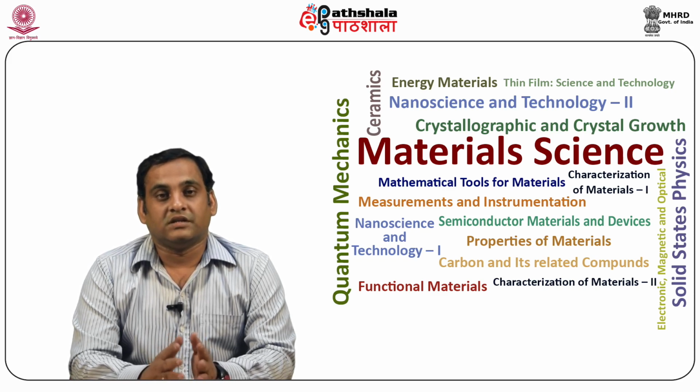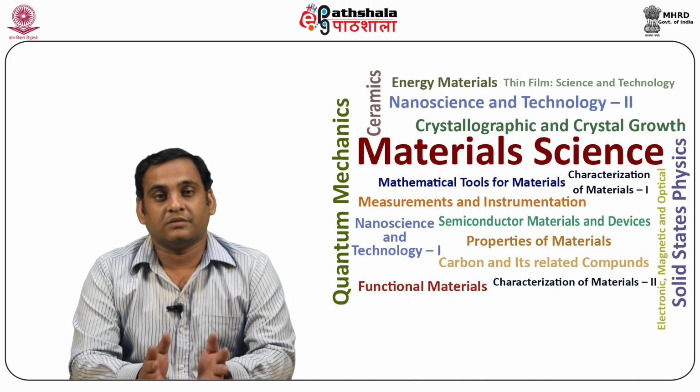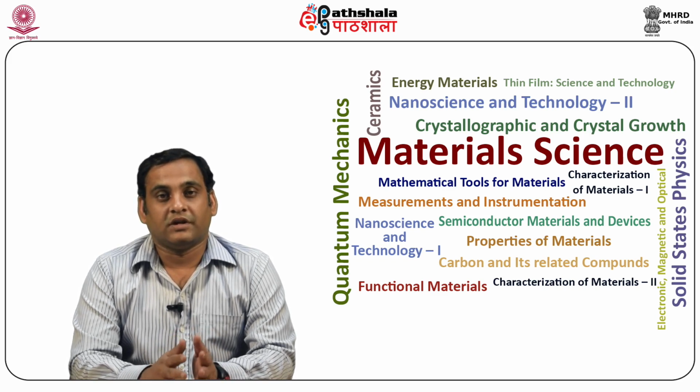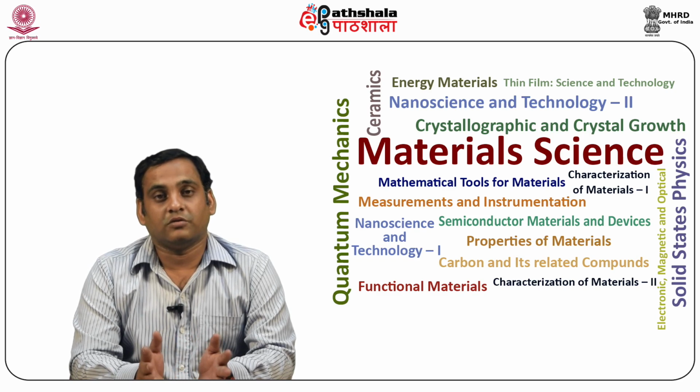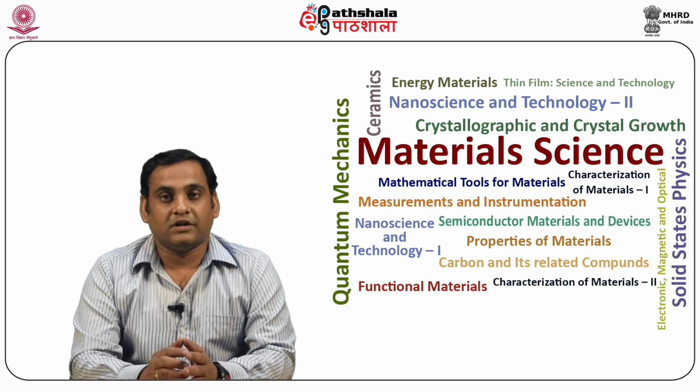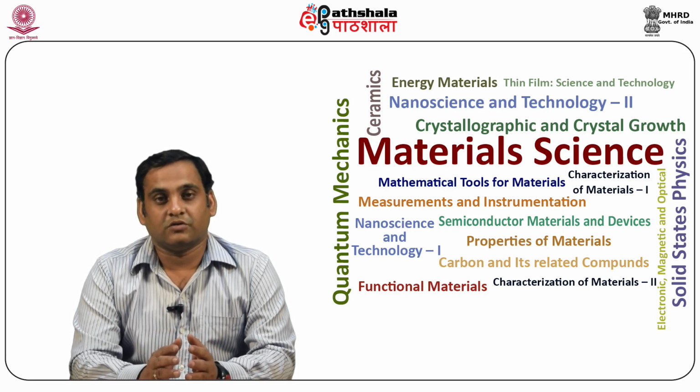Equation 3 is based on a particular definition of the demagnetized state, namely one in which all possible types of domains have equal volumes. For example, in a cubic crystal like iron with 100 easy directions, this state is one in which the total volume of the crystal is divided equally among 6 kinds of domains: [100], [1 bar 00], [010], [01 bar 0], [001] and [001 bar].